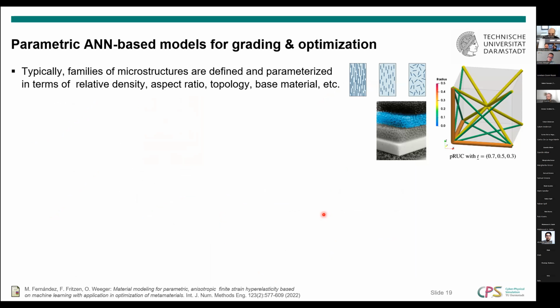Now, when we are looking into metamaterials or microstructured materials, we typically have families of microstructures, meaning that you could have a fiber reinforced material where you're able to change the volume fraction of the fiber content, or where you're able to change the orientations, or you have a foam where you're able to change the volume fraction of the foam or the pore size and these kind of things. So what you want is a material model that is parameterized in terms of these design variables of the microstructure.